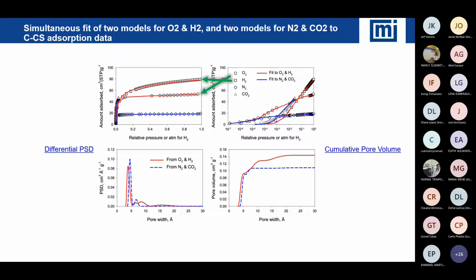Okay. If we change a little bit and we start looking at chars, and char is always very challenging for characterization. Notice things switch a little bit when we look at char. So for example, now hydrogen has the highest amount of adsorption, and you see that on the top, that the hydrogen capacity for this char is greater than the oxygen capacity, the nitrogen, or the CO2.